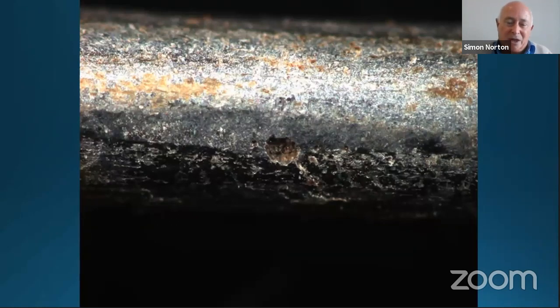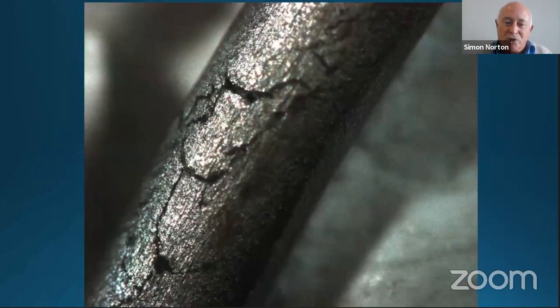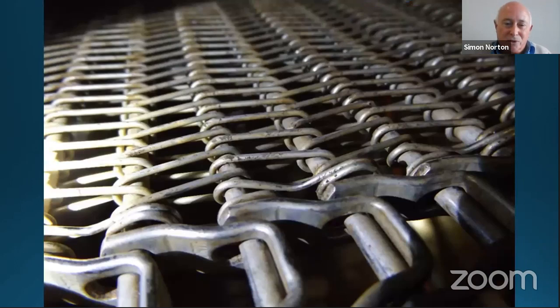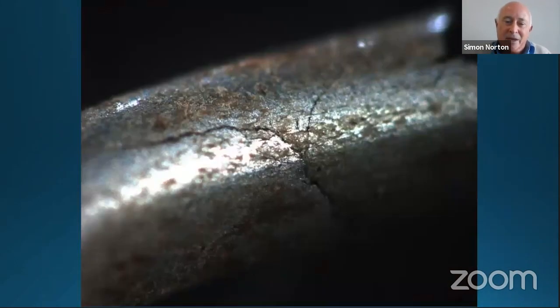This is what it looked like when we magnified the belt, magnified the wires. You could see the pits, and then we saw the stress corrosion cracking and the cracks all over the wires. And from there, it was relatively easy to get to the solution. This is what the belt looks like very close up. That's one of the stress corrosion cracks in the wires.